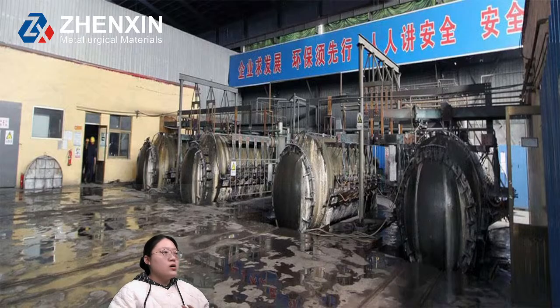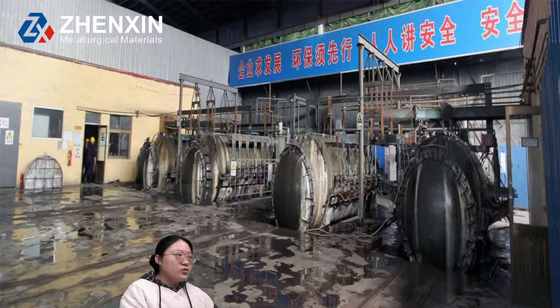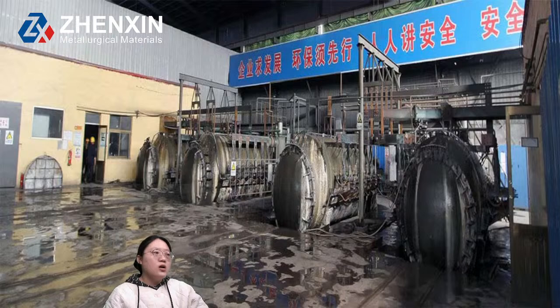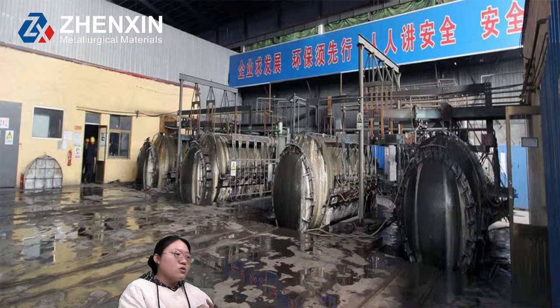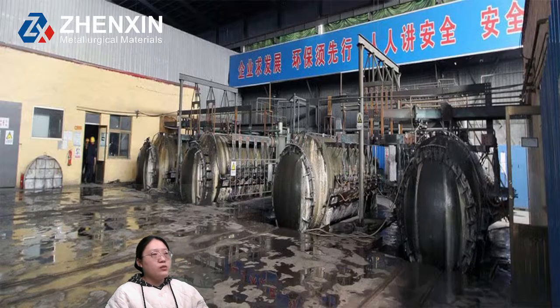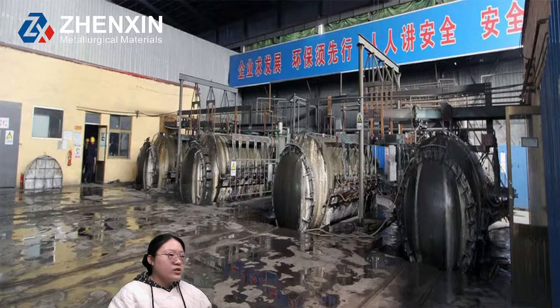If you choose the wrong size of nodulizer, you will find that if it is too fine, you get violent reactions, and if it is too coarse, you get incomplete reactions. So choose the right size.